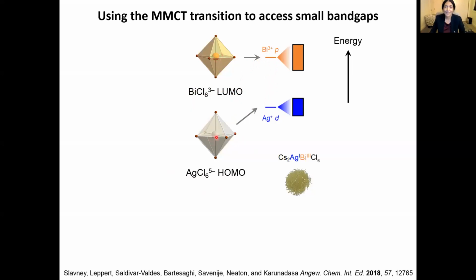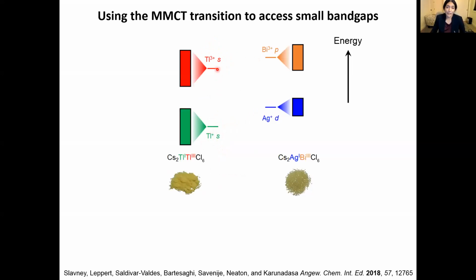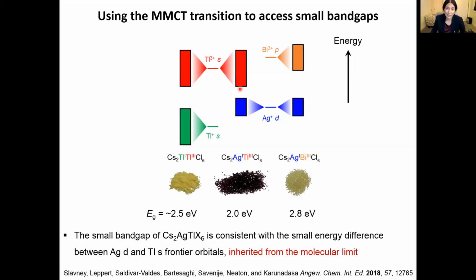Of these molecules. And likewise, I can look at this thallium-1, thallium-3 double perovskite and extrapolate from the band structure to the bands. And this tells us that if we were to pick molecular orbitals, so this is the metal hexahalide, molecular orbitals that inherently were close together, we can then form double perovskites with unusually small band gaps. So the band gap of the silver thallium perovskite is much smaller than your standard double perovskite for 2 reasons. One is because we are starting with molecular orbitals that were already close together. And the second point is that s orbitals are fluffy and dispersive, and they interact very strongly with each other, and therefore any band formed by s orbitals is more dispersive.